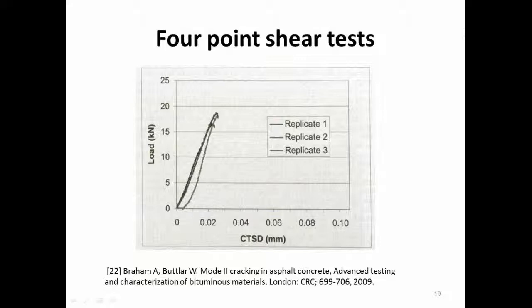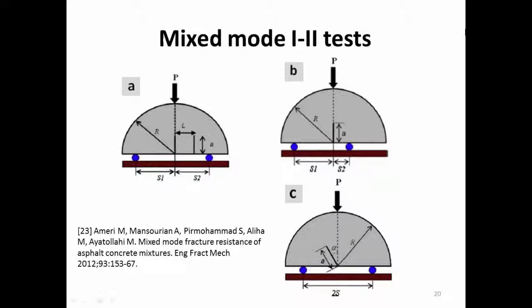But anyway, we have this data, we know what the mode 2 graphs look like. And then, as I said, in a real condition, the crack seldom happens in a single mode. So there will be mixed mode. Here are some of the representative mixed mode tests. For example, in the classical SCB test, we have the notch here. But if we shift the notch from here to here, the crack will be a combination of mode 1 and mode 2. The other thing you can do is, instead of shifting the crack, you just shift the support, and you will also get a similar effect.